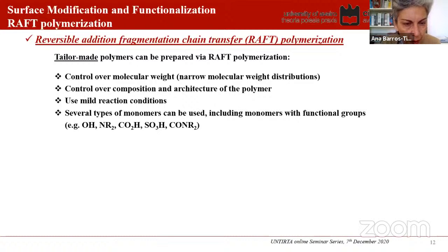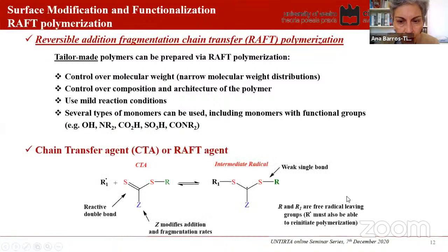Also, we can use mild reaction conditions, and we can use several types of monomers, including monomers with functional groups such as hydroxyl groups, carboxylic acid groups, amides, many different types of functional groups, because it's a very tolerant type of polymerization mechanism. For that, we use a chain transfer agent called CTA or RAFT agent. As you probably know, it is basically a dithioester, sometimes also a trithioester. It varies, but at least we have a dithioester